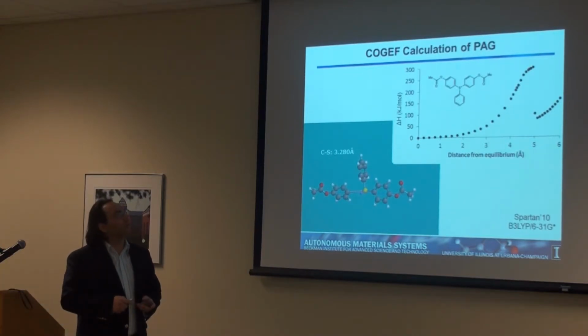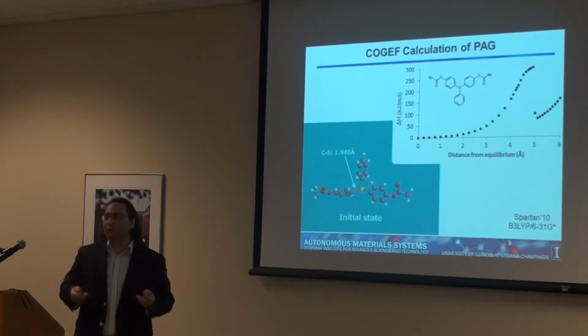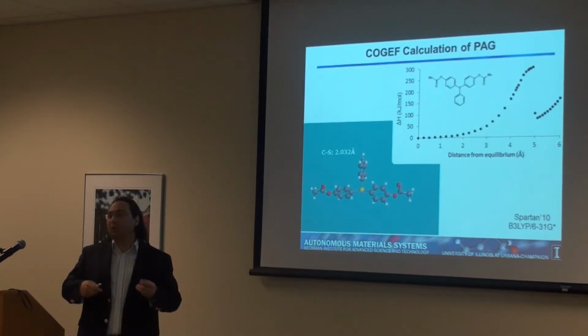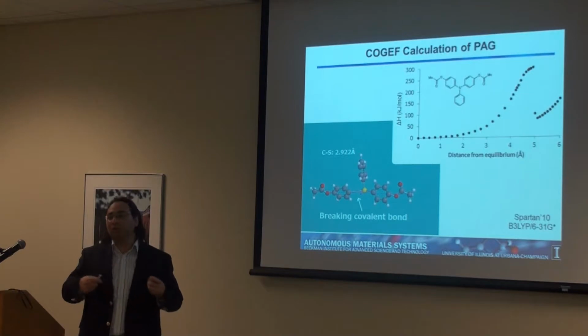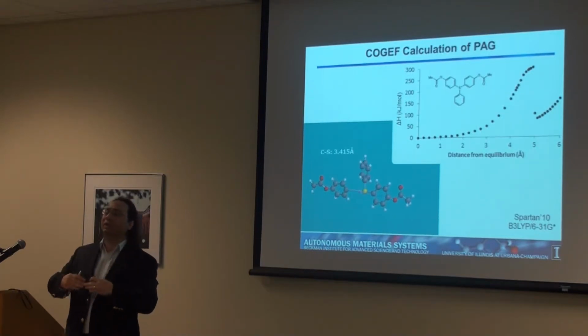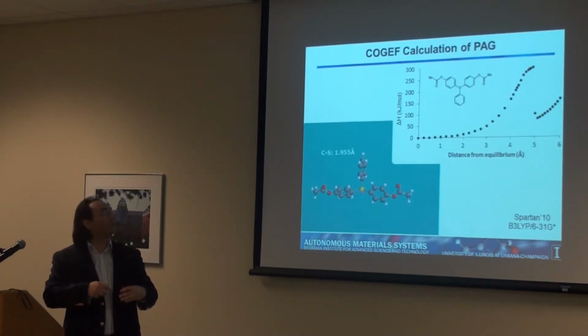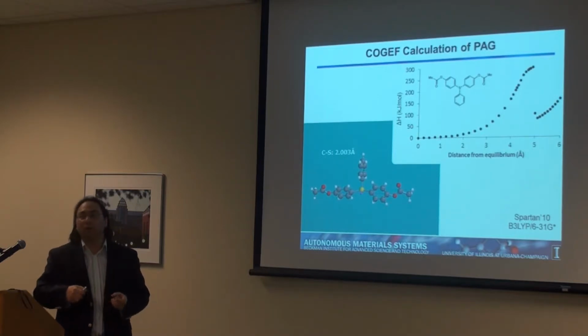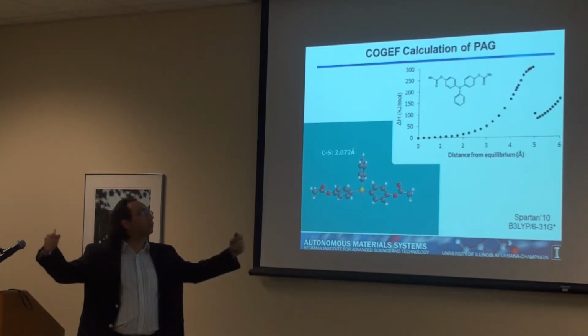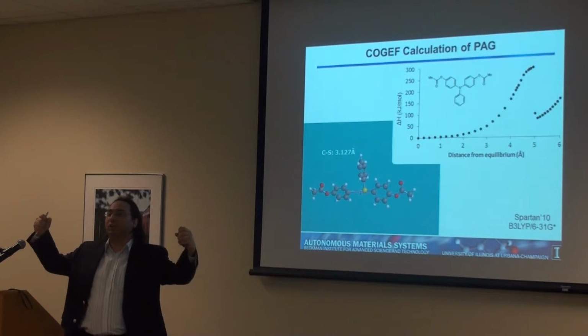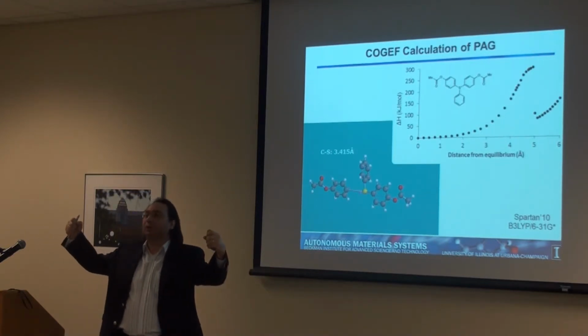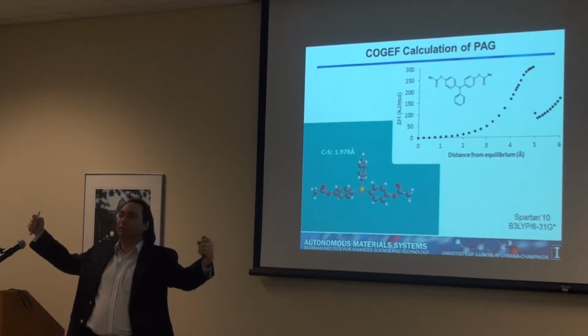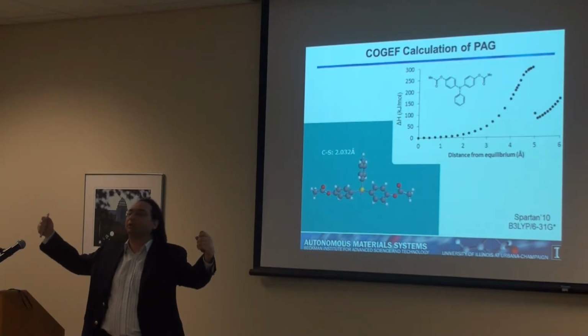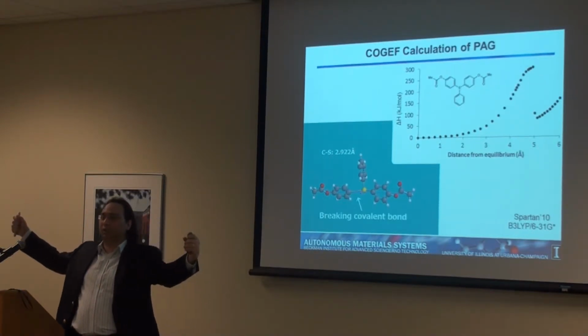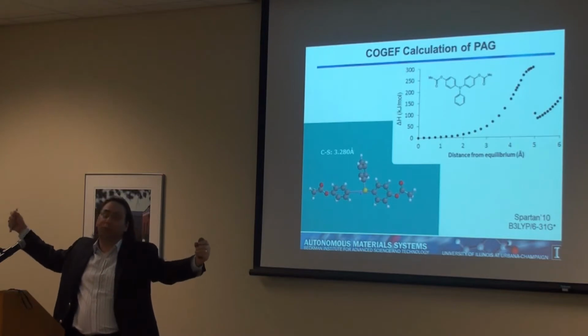And basically what we do, we take this molecule, we tell the computer, minimize this molecule, which means just change all the bonds and angles until you get to the lowest energy possible. So that lowest energy possible we call 0. And then we take the two arms, so the two last carbons, and we say, okay, this is the distance of equilibrium. Increase it by a little bit and minimize again, but keep that distance constant. Increase it a little bit more, increase it a little bit more, increase it a little bit more.